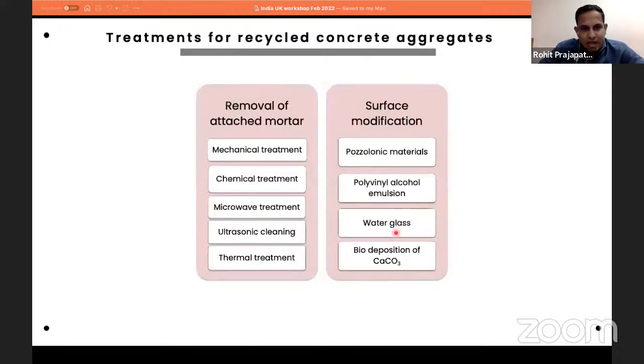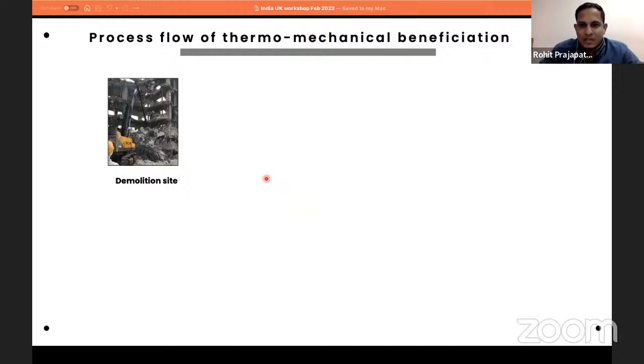So there are methods to treat the aggregates, which could be classified into 2 types. One is removal of the attached mortar. We can use mechanical and chemical treatments, microwave and conventional heating, or ultrasonic cleaning. And there are other methods which are focused on modifying the surface of the aggregate using fine materials or chemicals. So this presentation will be focusing on the thermal treatment, or the thermomechanical beneficiation technique.